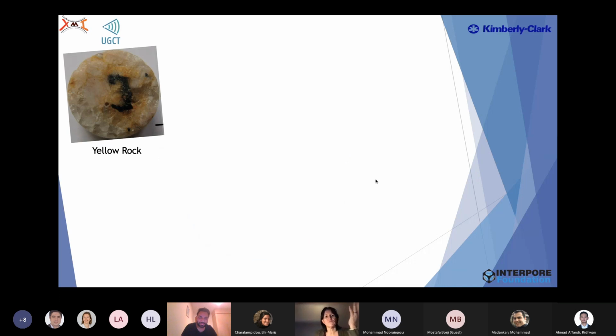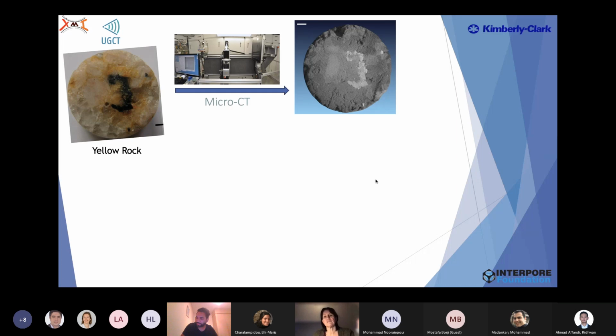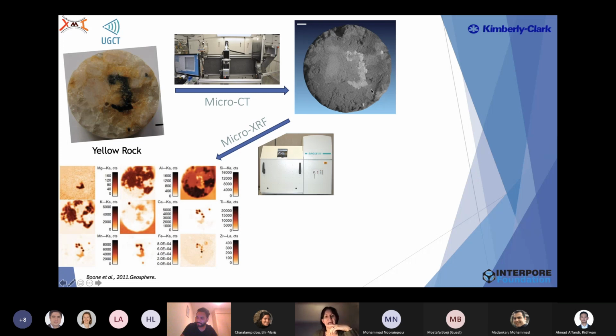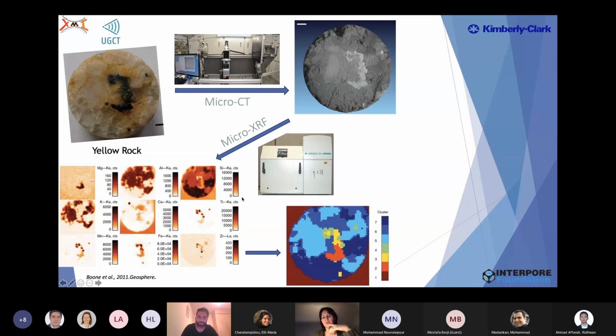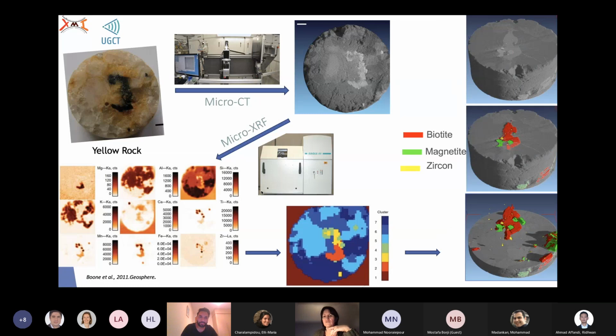In the past, we did this by first taking a rock and scanning it with micro-CT. We could distinguish different gray values because of the difference in chemical composition and average atomic number. Then we took the sample to a micro-XRF scanner and got information about the chemical composition, and then by cluster analysis we could say which kind of minerals they were.